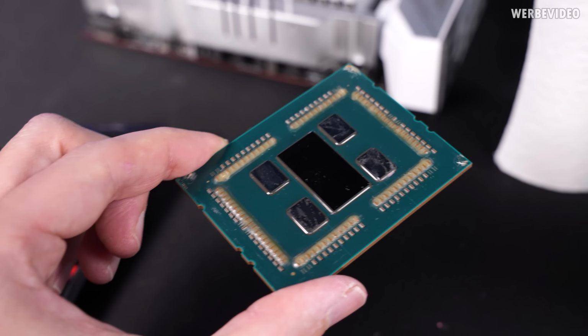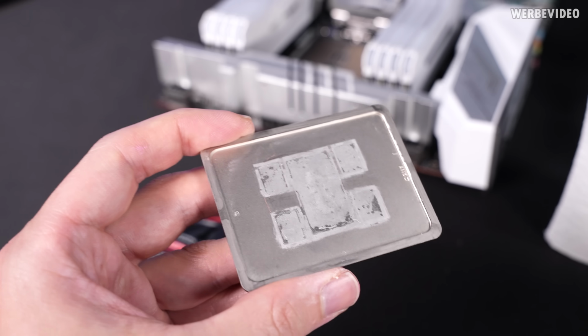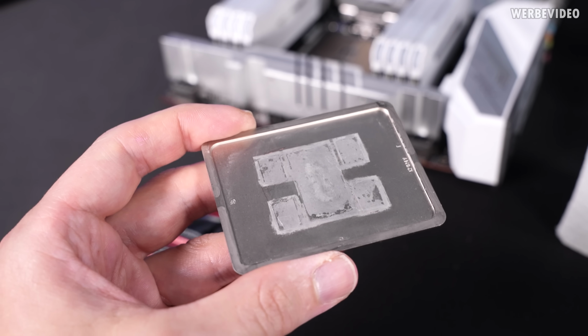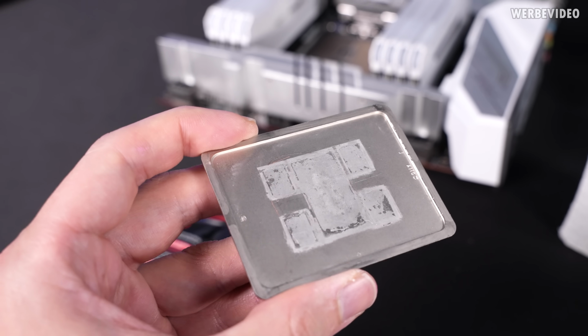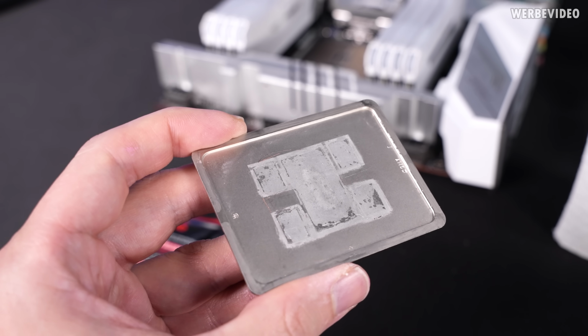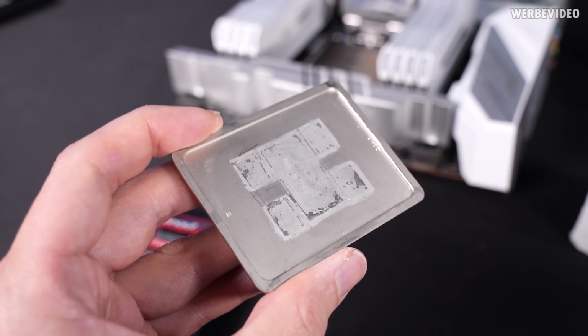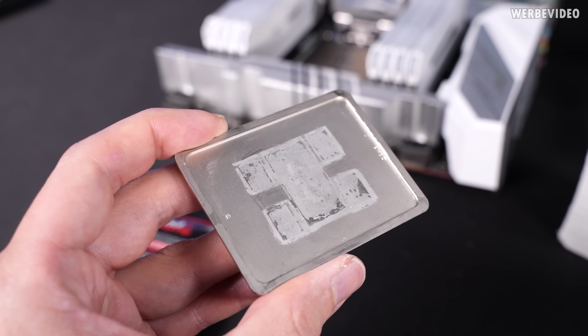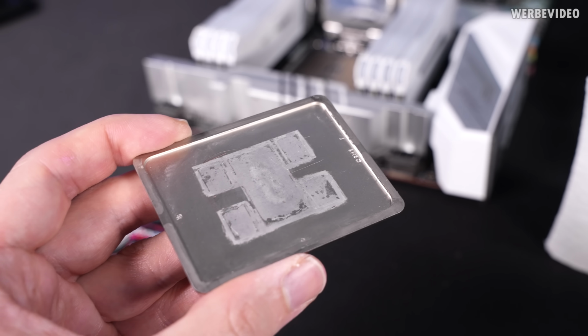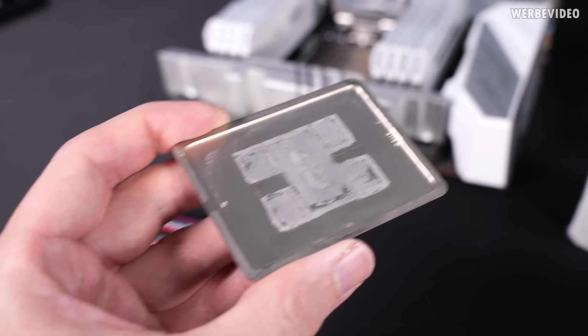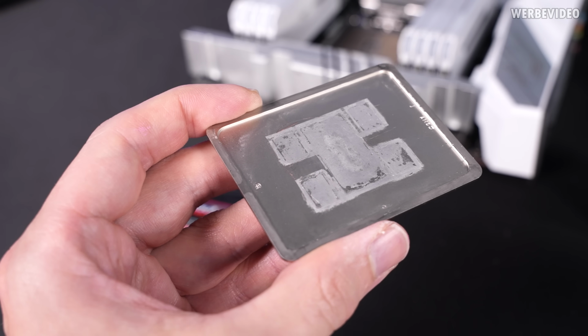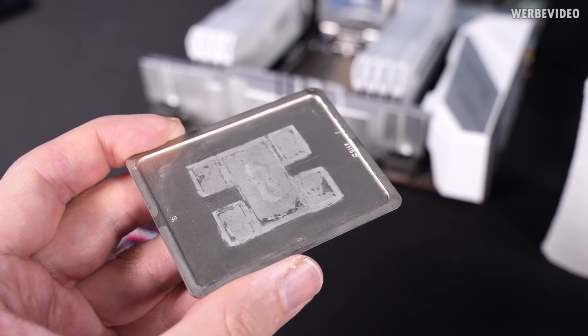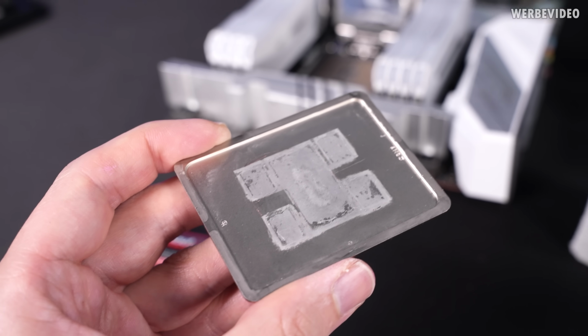So cleaning of the CPU was no problem at all. On the heat spreader though, it looks different. Also, as expected, I wiped it off like 10 times with different cleaners, but as you can see, there are still residues, both from liquid metal and also the darker areas that we inspected under the scanning electron microscope, which is basically residues and also embrittlement by the gallium.